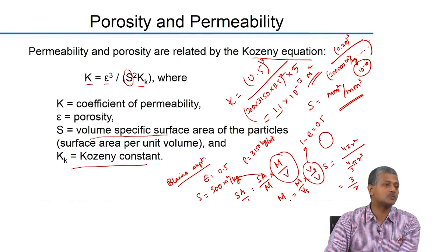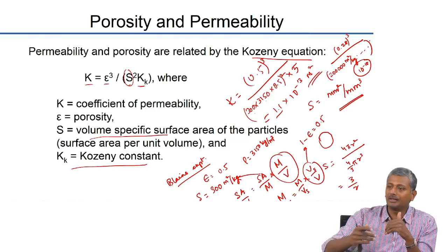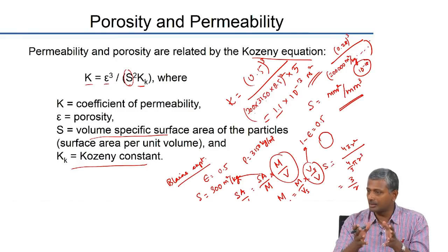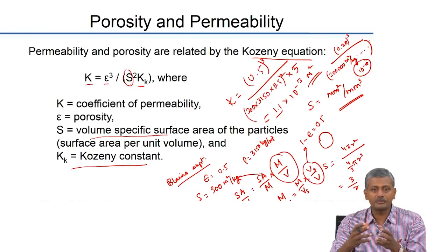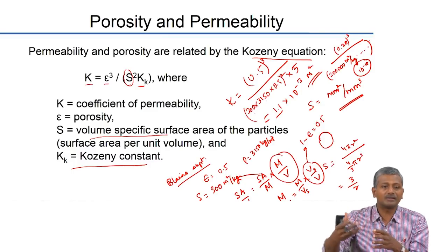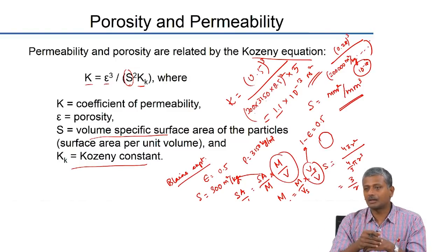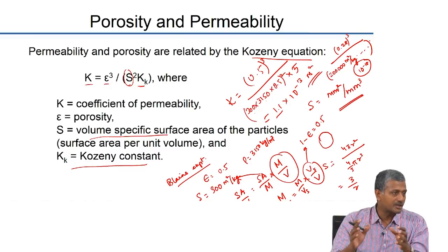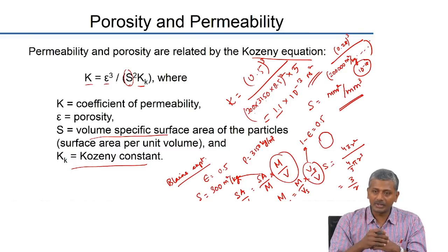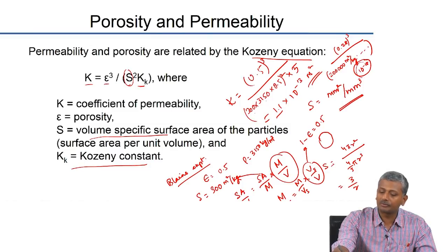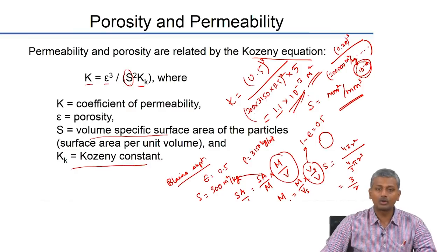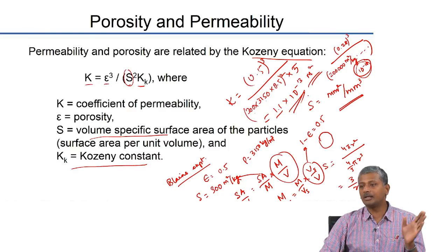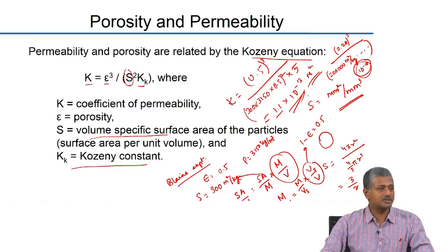So again, we are talking about systems where you have a gradual reduction in permeability as hydration happens. You can imagine when cement and water are just mixed together, the water forms your capillary porosity and the entire water system is essentially your permeable system. But as more and more hydration happens, as more CSH gets formed, more of the volume surrounding the cement is getting transformed into CSH. And of course, it is not just CSH, it is calcium silicate hydrate plus other cement paste compounds like calcium hydroxide and so on. So there will be capillary porosity, but the overall porosity may lead to a permeability several orders of magnitude lower than your initial permeability in the system. So your permeability evolves when hydration happens, and you can actually see that from this expression itself.